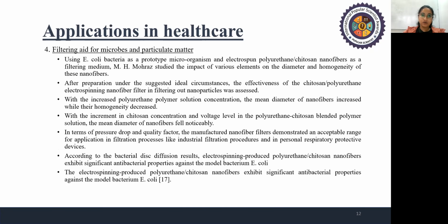Another one is the filtering aid for microbes and particulate matter, using E. coli bacteria as a prototype microorganism and electrospun polyurethane chitosan nanofiber as a filter medium. The researchers studied the impact of various elements on the diameter and homogeneity of these nanofibers. After preparation, he suggested the ideal circumstances, and the effectiveness of the chitosan and polyurethane electrospun nanofiber filter in filtering out nanoparticles was assessed. So with increased polyurethane polymer solution concentration, the mean diameter of the nanofiber increased while their homogeneity decreased.